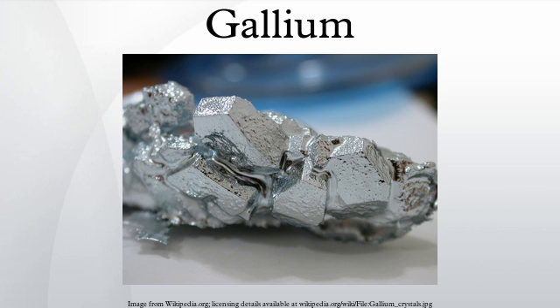Gallium(III) sulfide, Ga2S3, has 3 possible crystal modifications. It can be made by the reaction of gallium with hydrogen sulfide, H2S, at 950 °C. Alternatively, Ga(OH)3 can also be used at 747 °C: 2 Ga(OH)3 + 3 H2S → Ga2S3 + 6 H2O. Reacting a mixture of alkali metal carbonates and Ga2O3 with H2S leads to the formation of thiogallates containing the Ga2S4^2- anion.